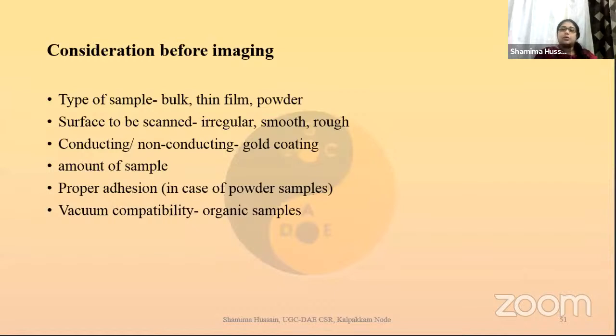But certain things are common. We need to have the surfaces to be more or less regular. That gives you a wider view. So if your sample is not regular, what do we do? In that case, we need to mount it properly in a mount and then study it. Why is this regular surface required? Because if you have uneven height, you may have the chance of hitting the pole piece with your sample. In that case, it would be a very terrible kind of damage to the system.